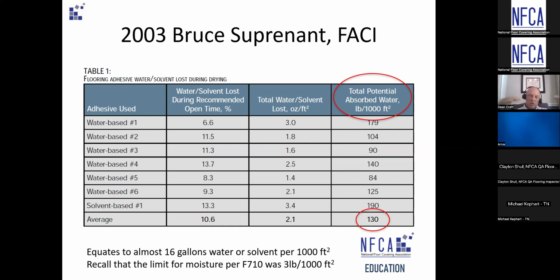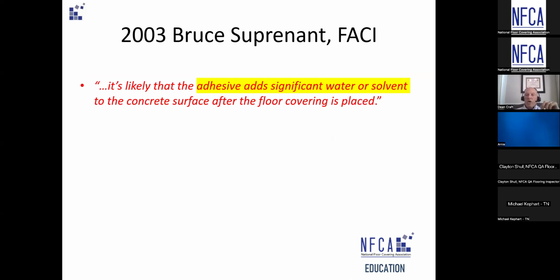So then what really induced the failure? This is one of those things that causes a conundrum, but it's just some data a lot of people are not aware of. And so what they determined is that the adhesive itself likely adds a significant amount of water to the surface of the concrete post moisture testing. The impact on that concrete is never determined because there's no post adhesive spread moisture test to verify the concrete is still within the ranges.